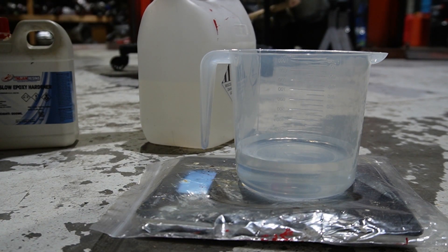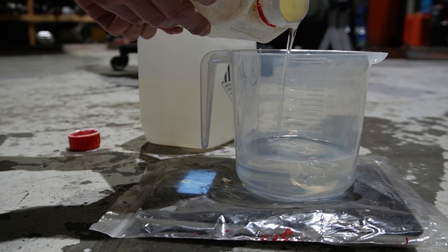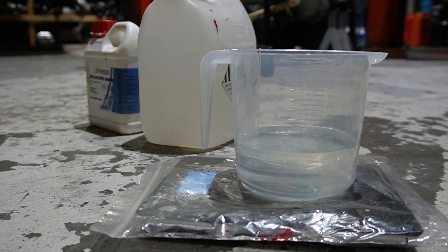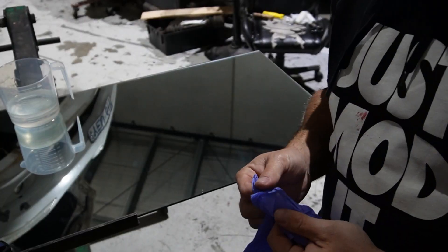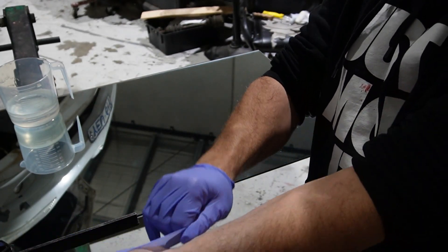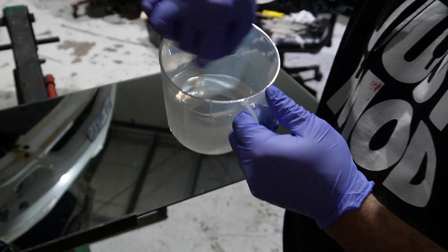Now it's up to you how much you want to use. Realistically it should be about one to one — for every gram of mat we're going to put on the job, you can weigh out one to one in resin. We're going to go a little resin-rich in this instance so we don't end up without enough and have to quickly mix more. I'd rather just leave a little bit in the pot and let it go off. Now mix it up — if you can see any swirl patterns in there that means it's not mixed enough. One thing I'd like to mention: you really should use gloves — not for any chemical reasons, but this stuff is super duper sticky and water doesn't wash it off. So wear gloves, trust me. Mix it for a couple of minutes, and normally they direct you to tip it into another tub and mix again.